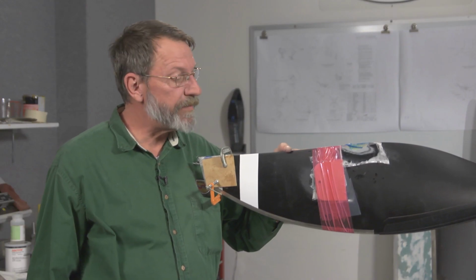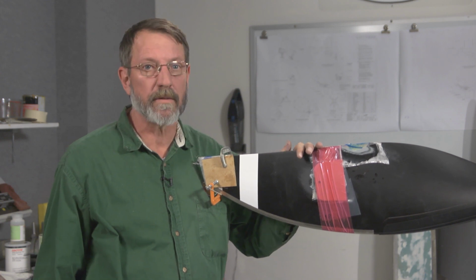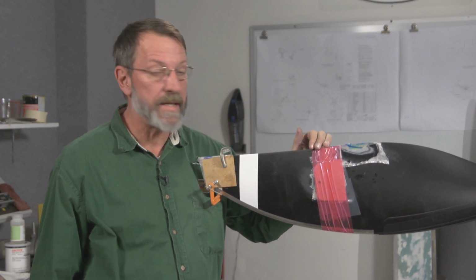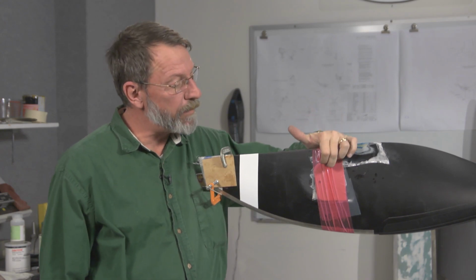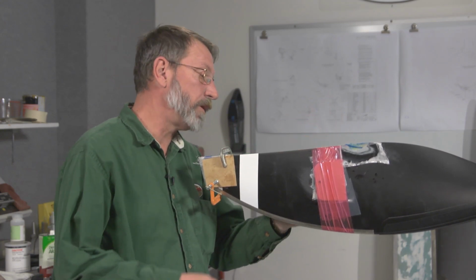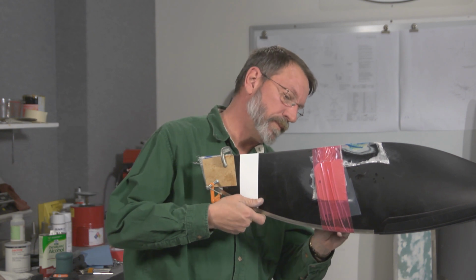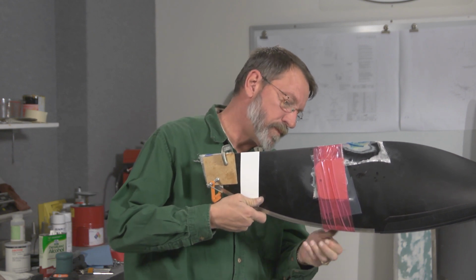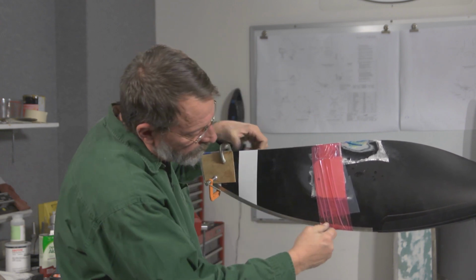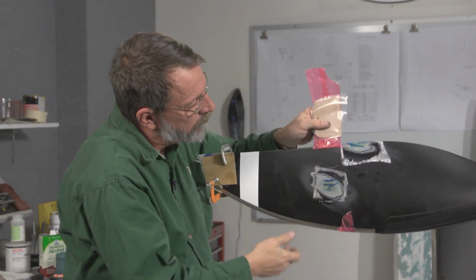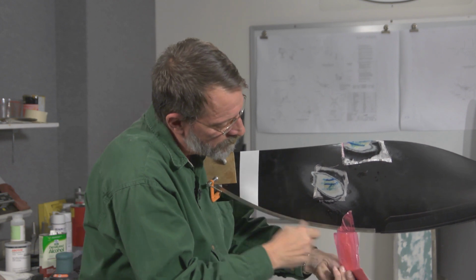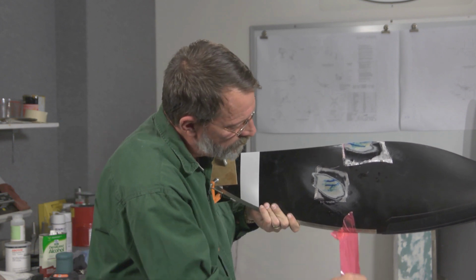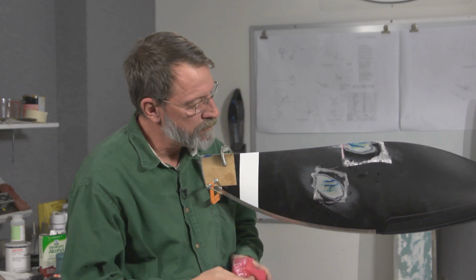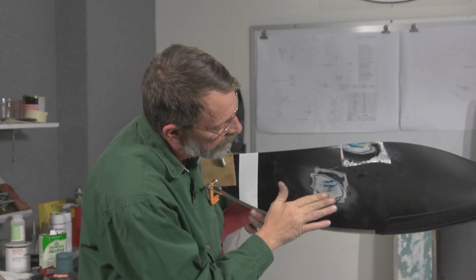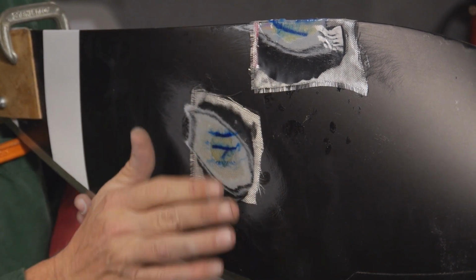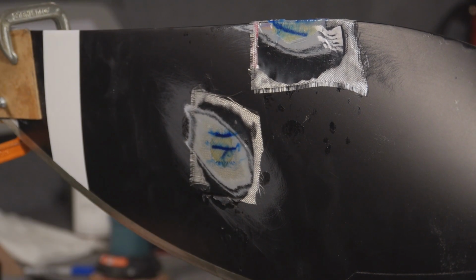The adhesive for the repairs has cured. It takes 12 hours at room temperature to cure the adhesive. So now we're going to remove the tape and see how the repairs have come out. That seems like a good repair.